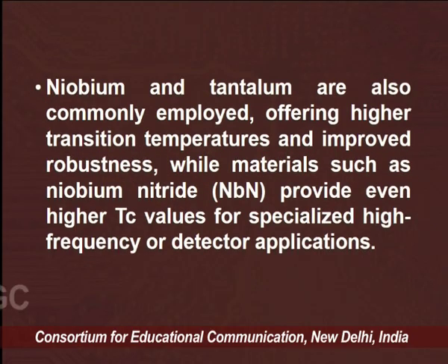So, aluminum is used. Niobium and tantalum are also commonly employed, offering higher transition temperatures and improved robustness, while materials such as niobium nitride provide even higher Tc values for specialized high frequency or detector applications.